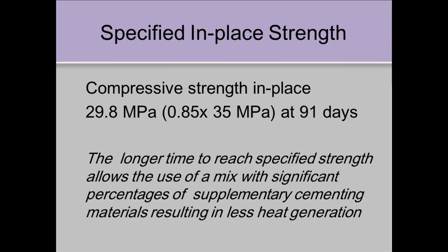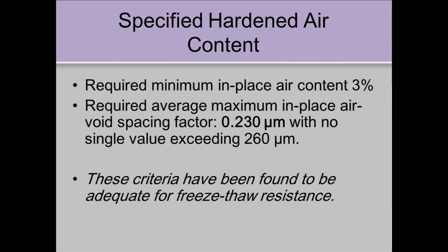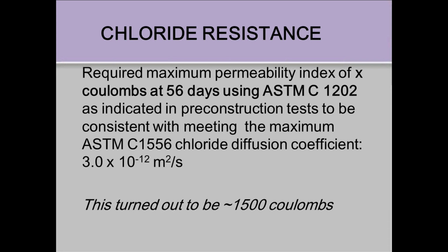We said, look, if you want 35 MPa, make it at 90 days, but if we're going to test on cores, you've got to take 85% of that for acceptance based on cores, so it's only 30. We said we take in-place air content and air void distributions rather than fresh air contents, at least for the pre-qualification specification, and we allow them to use the rapid chloride test. For service life, because they want 100 years from these structures, they use a chloride diffusion test. We're saying you've got to calibrate that, because from a construction acceptance point of view, a diffusion test takes about 3 or 4 months to finish, and it's a useless test for acceptance criteria. It's great for pre-qualification, useless for acceptance.